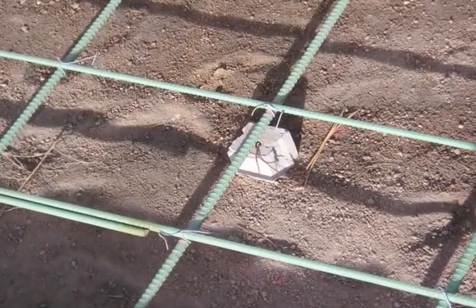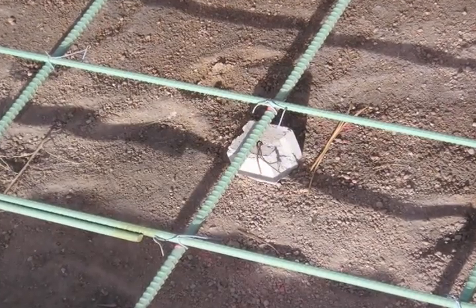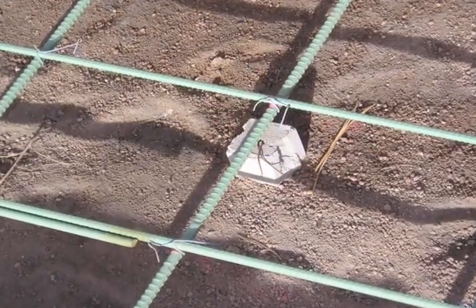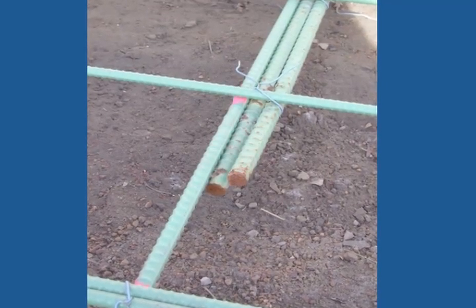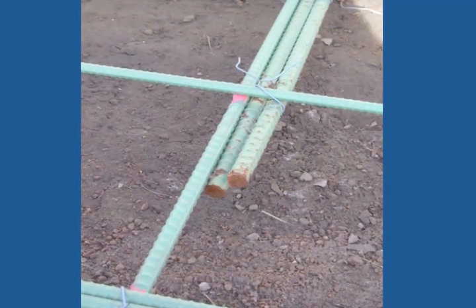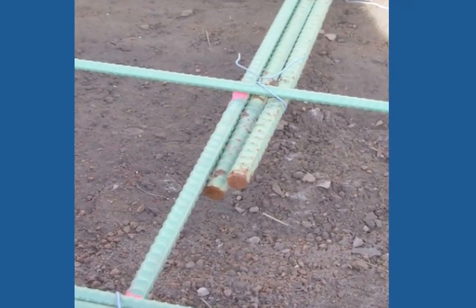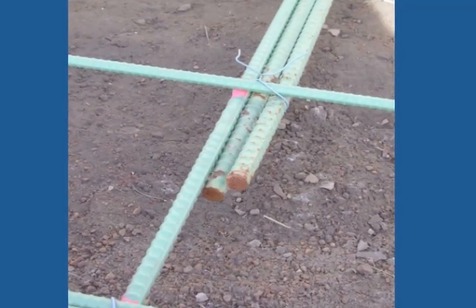However, for this to be successful, all parties involved with transportation, handling, and placement of this must be careful. And even with field cuts, such as is shown here, an epoxy compound patch must be applied to prevent localized corrosion at that location and ultimately shearing of the bar. Unfortunately, though, in too many cases, proper handling techniques are not utilized, and in fact, the ribs of the rebar are scraped. As the workers strike the tie wires down, they strike the epoxy coating of bars beneath, causing dings and other defects in the epoxy coating, and in many cases, the bar begins corroding even before the concrete is cast around it.